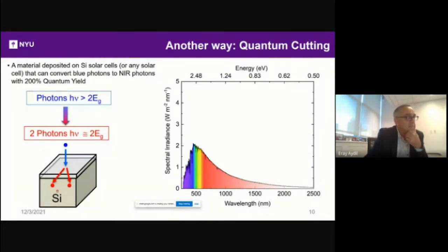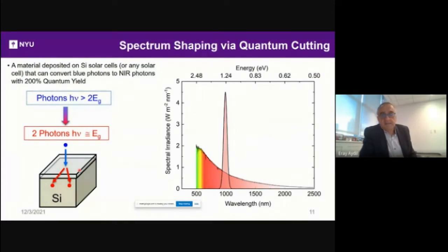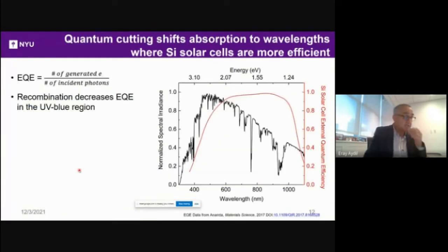So you'd like to put a magic material on top of a silicon solar cell, and that magic material takes all the blue and UV photons and with 200% efficiency creates near infrared photons, and that's called quantum cutting. So that would basically make the spectrum look something like this. So it decreases the losses due to relaxation to band edges. So you're essentially exciting to the band edges directly, not deep into the bands, okay? So that's one advantage of having a quantum cutting material.